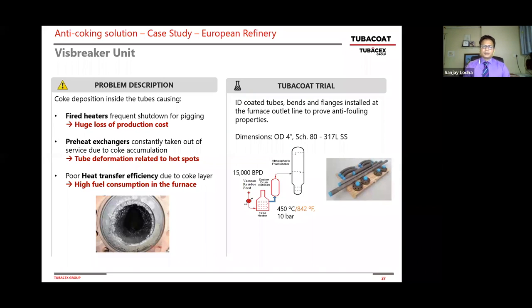So this one is a European refinery, a visbreaker, 15,000 barrels per day. You can see the picture of the visbreaker with the furnace and upstream heat exchanger. They have quite frequent shutdowns for pigging. To be accurate, they do two piggings per year, and that is about 8 days of shutdown. That's a significant loss of production. Then they have a preheat exchanger upstream of the furnace that is also taken out of service due to coke accumulation and poor heat transfer, which gives you higher fuel consumption.